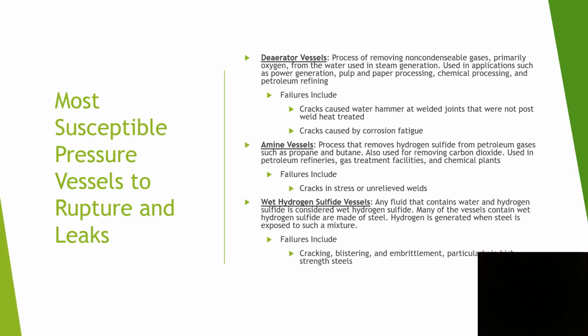Some of the most susceptible pressure vessels to ruptures and leaks are the deaerator vessels. They basically remove non-condensable gases, primarily oxygen, from water used in steam generation. It's used in applications such as power generation, pulp and paper processing, chemical processing, and petroleum refining. The failures include cracks caused by water hammer at welded joints that were not post-weld heat treated, and cracks caused by corrosion fatigue. Then you have amine vessels, and they remove the hydrogen sulfide from petroleum gases such as propane and butane. Also used for removing carbon dioxide, used in petroleum refineries, gas treatment facilities, and chemical plants. The failures include cracks in stressed or unrelieved welds.